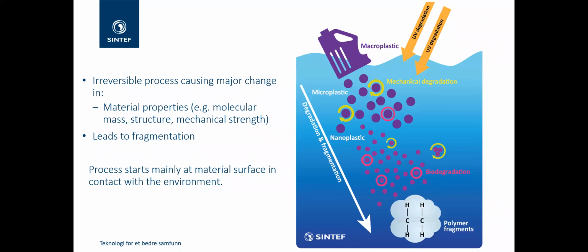The thing probably to keep in mind with this degradation is that it's an irreversible process, and it can cause quite major changes in material properties. That includes things like molecular mass, the structure, the mechanical strength. Also, I haven't listed it here, but also chemical changes, these oxidation processes, they're changing the chemistry, particularly on the surface that's in contact with the environment. And it's this that leads to the fragmentation process where you go from a macroplastic litter item through the microplastic size range, nanoplastic, and down eventually to polymer fragments.